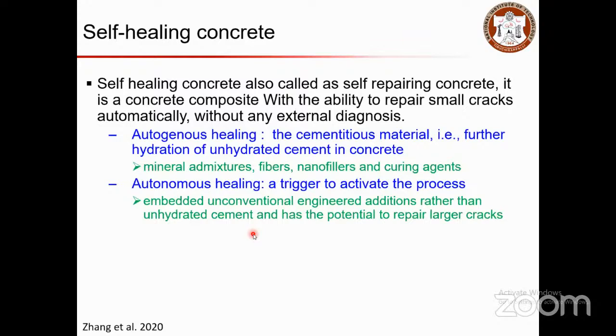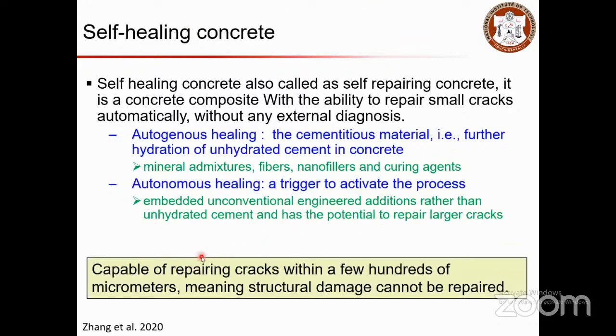And in autonomous healing, there is a trigger. So you activate something so that there is some reaction that will be induced to repair the crack. So with embedded unconventional engineered additions rather than unhydrated cement, it has the potential to repair larger cracks. So you can use self-healing as a control measure. This could be capable of repairing cracks within a few hundreds of micrometers. Meaning, if you have a structural damage with several large crack widths, or cracks falling or something, in those cases this will not be helpful. This is for maintenance and control purposes. So in the initial stage, if you have such mechanisms that will help you to reduce the minor cracks, further crack growth that would result in a severe crack in the later stage will be prevented.